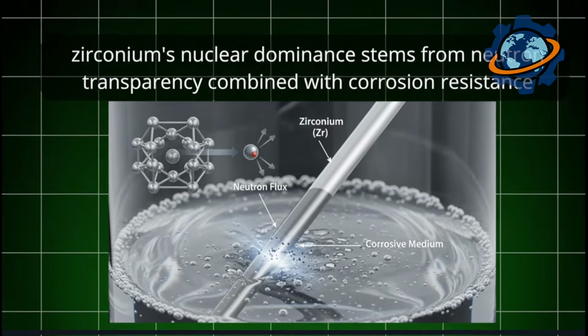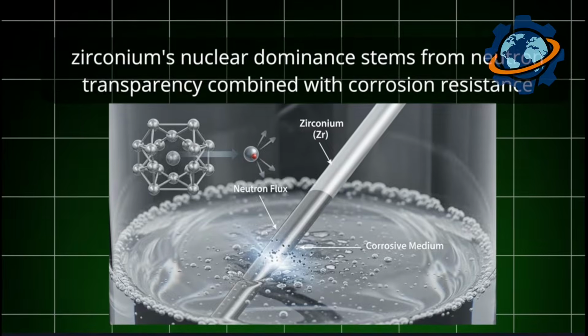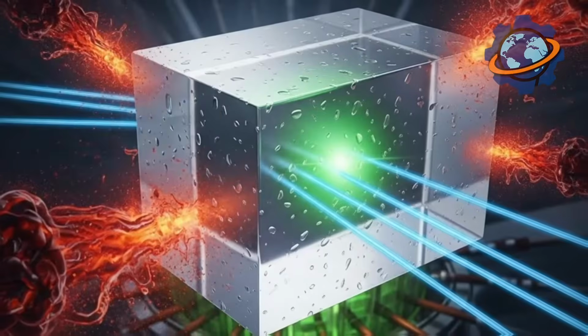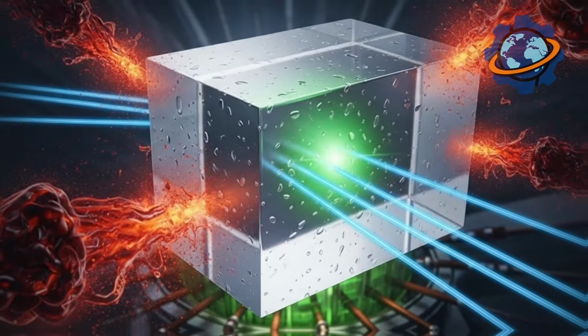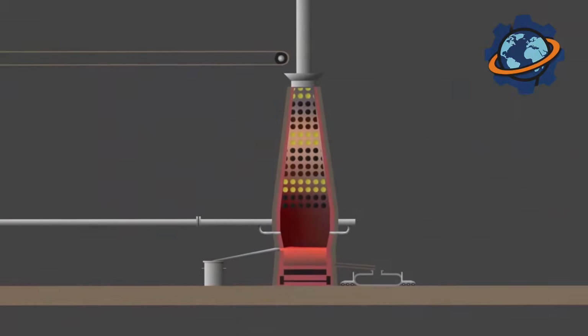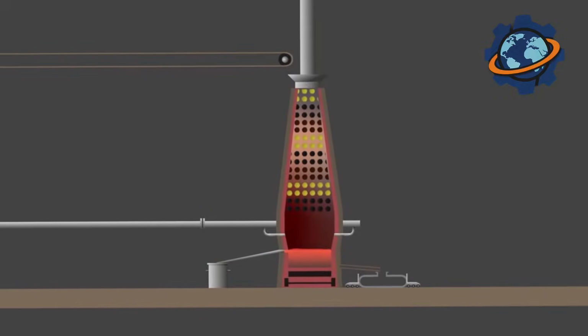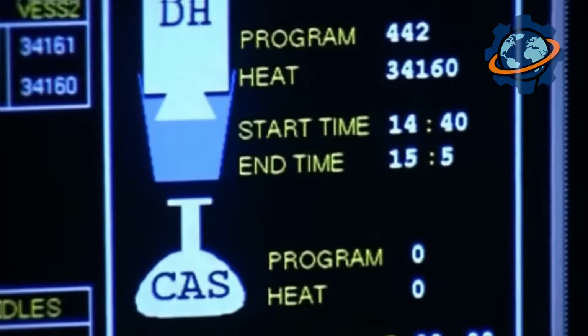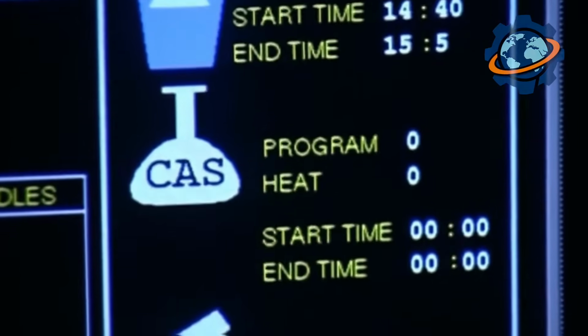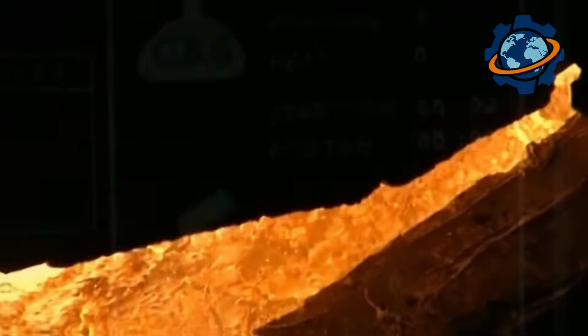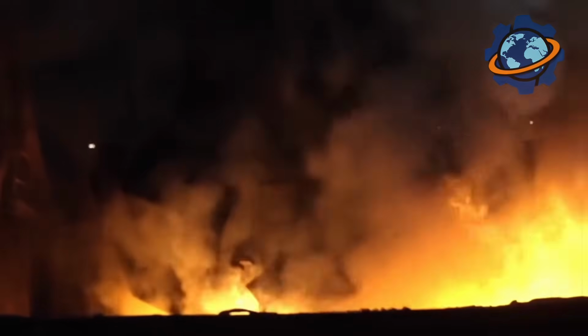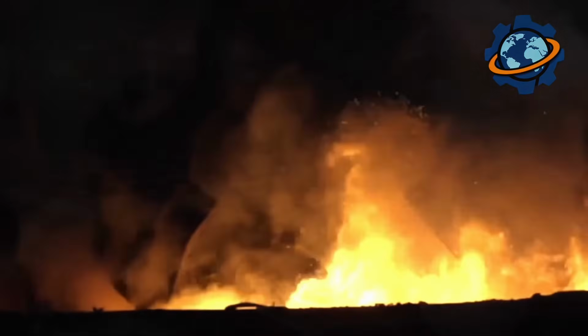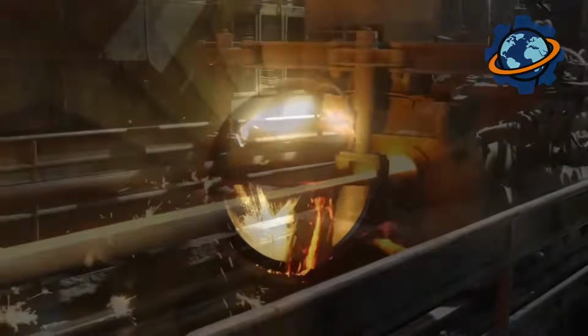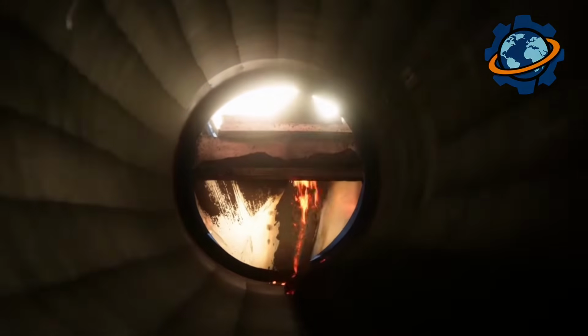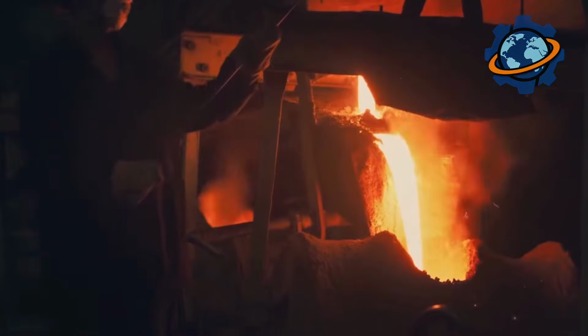Zirconium's nuclear dominance stems from neutron transparency combined with corrosion resistance. Most metals absorb neutrons, poisoning the reaction. Zirconium is essentially transparent to neutrons while withstanding high-temperature water corrosion for years. But zirconium has a dark side - it's pyrophoric. Fine zirconium powder burns spontaneously in air. During the Chernobyl and Fukushima meltdowns, zirconium cladding reacted with steam, producing hydrogen that exploded violently. The metal protecting us from radiation can amplify disaster.